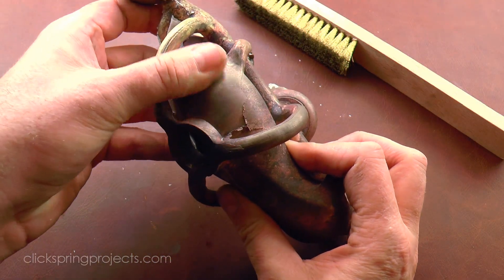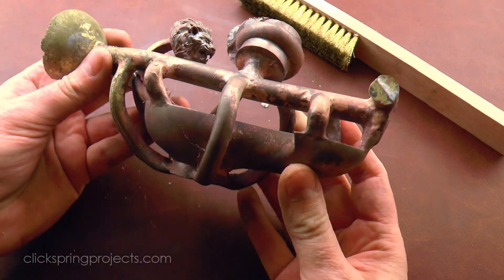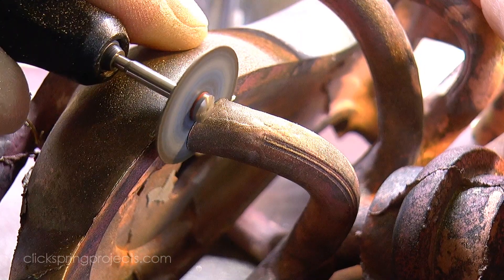There's some light flashing in parts of the casting surface, related to the cracking tendency that I mentioned previously, but overall the surface finish is ok. So it's on to the next stage of taking off the gate system and generally fettling the casting into a presentable state.